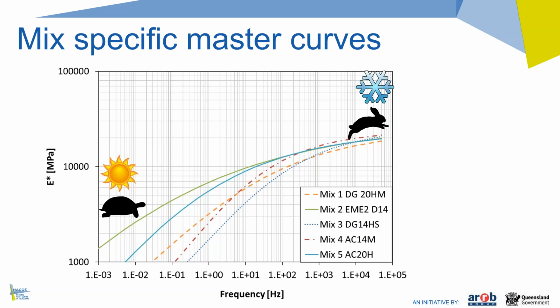So Eric, can you just explain how you get the design modulus, say for a certain traffic speed and temperature, from that master curve? Yes, well that is very much the same as we currently do with those relationships in Austroads. So we calculate the frequency under the traffic speed using the current Austroads equation to do that, and you set in your master curve equation the temperature to your design temperature, the weighted mean annual pavement temperature, and then the modulus value that you get, you then correct for the design air voids content that you're looking for.